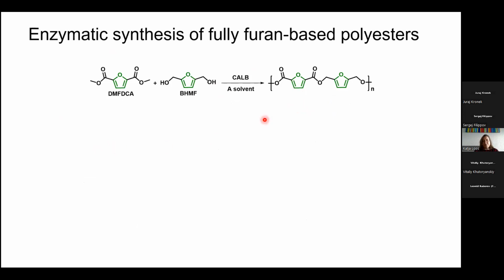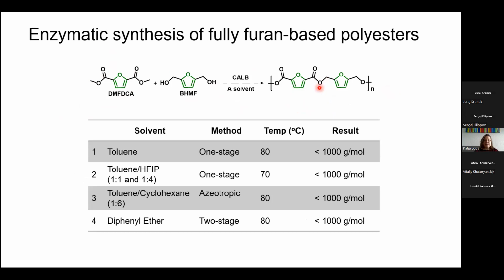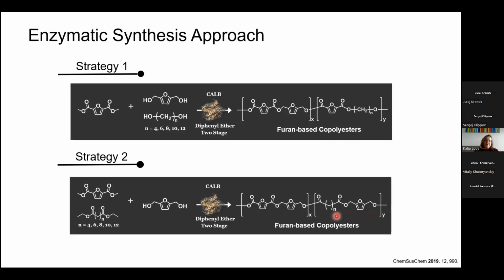And this is our holy grail, and we are not there yet. So we would actually really like to polymerize FDCA with BHMF, get this structure, and maybe also the polyamide. But this is really too bulky for all the enzymes we have yet. So you see, you get very low molecular weights. But Dina Mania, who was working on that, was developing a different strategy for that. So she was co-feeding this polymer. So we would actually like to polymerize this with this. Doesn't work. So she was co-feeding it a flexible diol or a flexible diacid, and then it really works. So we get high amounts of this structure. So we would actually like to have this structure, but here you get a high amount of this and a bit of this, and then it works.